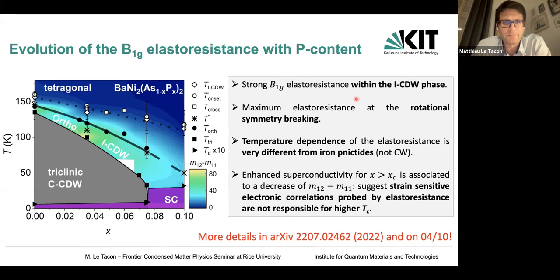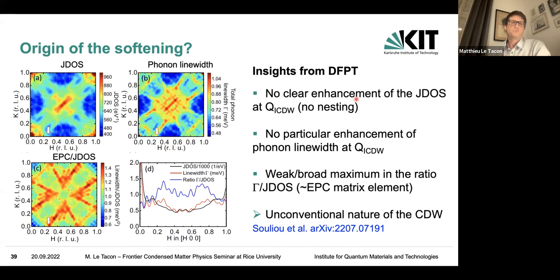Okay, so just to finish a bit here, we do have in our toolbox a few tricks to find out the origin of the softening and whether it's a normal Kohn anomaly or not. You can calculate, for instance, the joint density of states, and you see that there's no peak in the joint density of states at the Q of the instability. You can calculate the total phonon linewidth. Here it's really the contribution to the electron-phonon coupling of all the phonons, not specifically the soft one. But we've seen that the soft one is not the main contributor anyway.